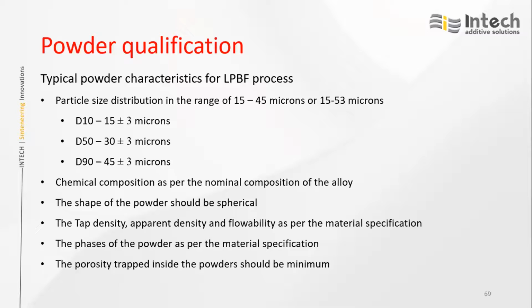We need to check the chemical composition as per the nominal composition. Shape of the powder should be spherical. Tap density, apparent density, and flowability are needed in order to freely spread the powder on the powder bed. Also the phases of the powder as per material specification - for example, if steel has an austenitic phase or 17-4 PH, different materials have different phases. We need to check whether the raw material has phases similar to the actual metal or not. And the porosity trapped inside the powder should be minimum.